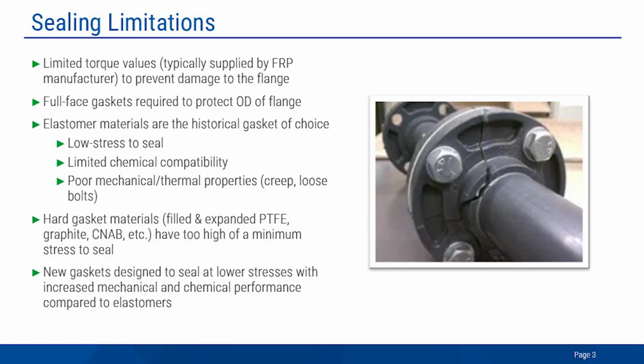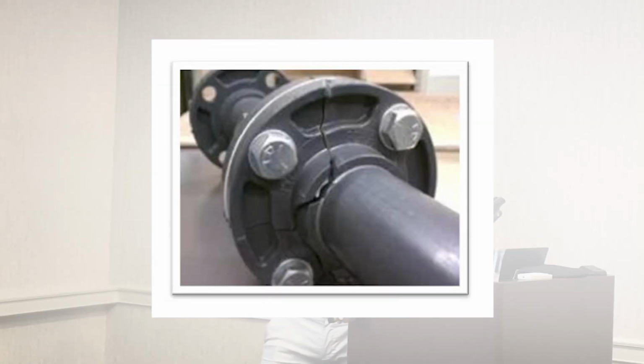The problem with hard gasket materials, like I said, any standard sheet cut material, so expanded PTFE, filled PTFE, graphite, compressed non-asbestos, is that the minimum stresses to seal for those are much higher than what you can achieve with a standard FRP flange. That picture there is obviously not FRP, but another non-metallic flange where I believe they were using a full face expanded PTFE gasket. It was leaking, and they did what any good mechanic would do, and they kept increasing the torque until it stopped leaking. But before they got to that point, they cracked it like you see there in that picture.